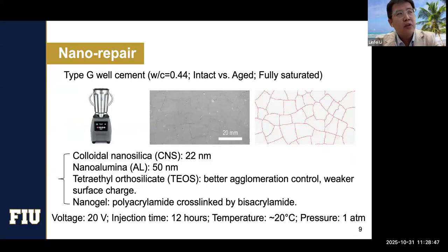So about this nanoparticle injection, or what we call nano repair, we started doing experiments. We use something called type G well cement. I don't think it's ASTM standardized, but it is listed in the API, American Petroleum Institute, standard. In the standard, they require a water cement ratio of 0.44. Imagine a water cement ratio of 0.44 without any aggregates. It's just like a liquid, very, very flowable. This is what they use for underground projects.